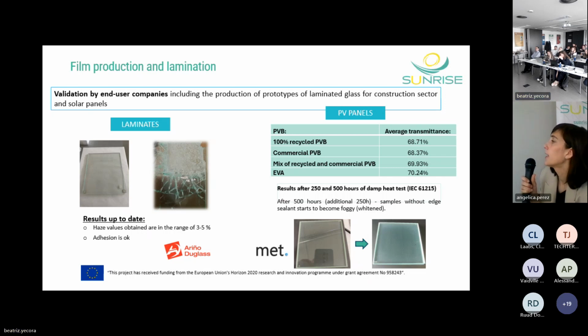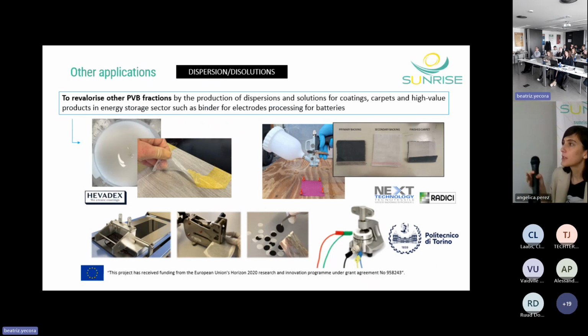And then for PV panels, Met is comparing the performance. Here it is more complicated because we have to compare with another different polymer, which is EVA. And in terms of transmittance, the transmittance could be very similar when comparing with EVA. But they have to make a lot of characterizations to be usable in solar field. So according to the damp heat test, in the first 250 hours, the samples work very well, both without edge sealant and with edge sealant. But after 500 hours, the samples without edge sealant start to become foggy. So what we are seeing is, if we use PVB, we need to make some modifications to the design to introduce these sealants to avoid increase of humidity. And that's about the lamination applications.